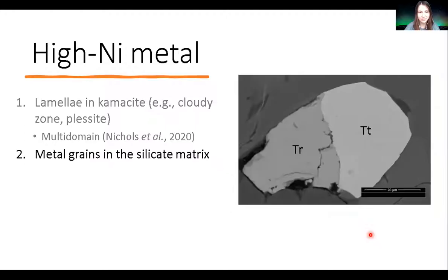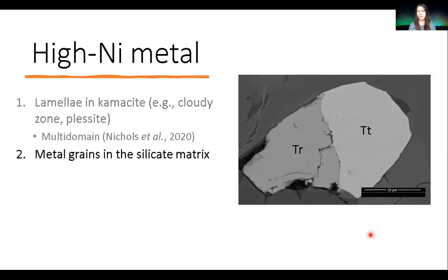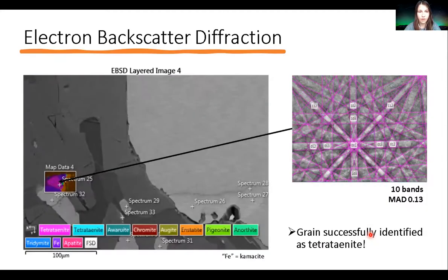Focusing on the silicate, it turns out that metal grains within the silicate matrix are actually fairly common. They occur together with either sulfide (troilite) or kamacite, and they are quite abundant with very little microstructure. All of these were identified with both EDS and electron microprobe as high-nickel — about 54 percent nickel generally — but this is not actually enough to identify tetrataenite because of compositional overlap between tetrataenite and taenite.